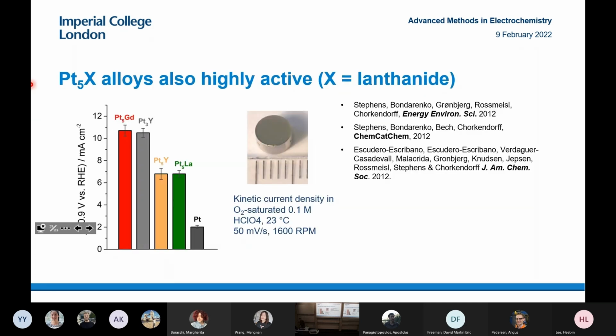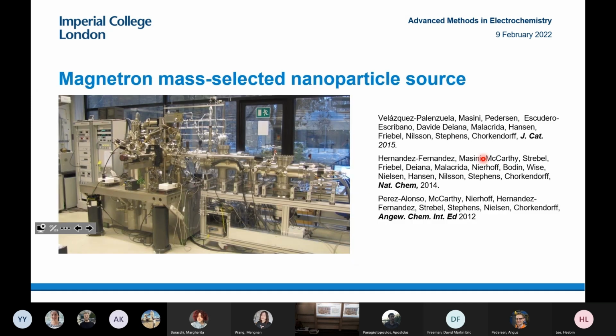So anyway, we also found other alloys of platinum and rare earths also really active, including platinum 5 yttrium and platinum 5 lanthanum. We also made them in nanoparticle form, and we found it was really difficult to chemically synthesize them because platinum is really easy to reduce, and yttrium is not. So we tried to synthesize them chemically, and we failed, and it was really frustrating. So we thought, okay, we're in a physics department, so let's use a physical method. We sputtered a target of platinum yttrium in the gas phase, and then we filtered out the right size and deposited it onto a planar surface.